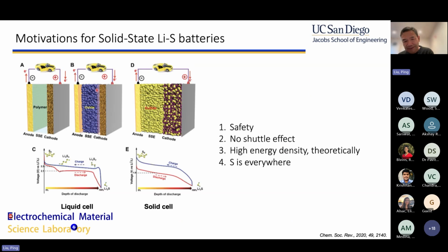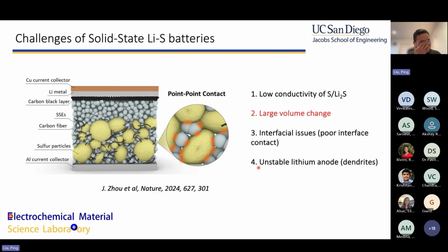The other approach we take is to move to solid state sulfur. We use a solid electrolyte instead of liquid electrolyte. Solid state is very safe. There's no shuttle effect because there's nothing to dissolve. There's no polysulfide dissolution. And you can make a very high energy density material. It turned out that this is even more difficult to do than liquid electrolyte, because in a solid state, we can't use the dissolution mechanism to get around this poor conductivity anymore, because nothing moves.